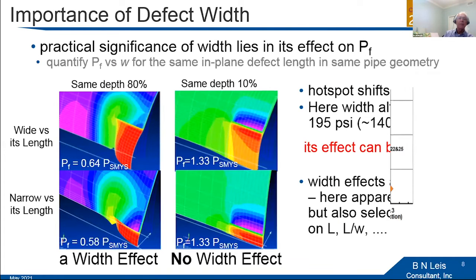I want to talk now briefly about the influence of defect width. For those that are familiar with failure criteria for corrosion and pipelines, they're primarily a function of the length and the depth of the defect. They completely ignore width. And yet if you think about width, the width being the dimension around the pipe, if you think about the width relative to the length, features that are large in area will bulge significantly, whereas features that are, for example, narrow but long don't bulge much.